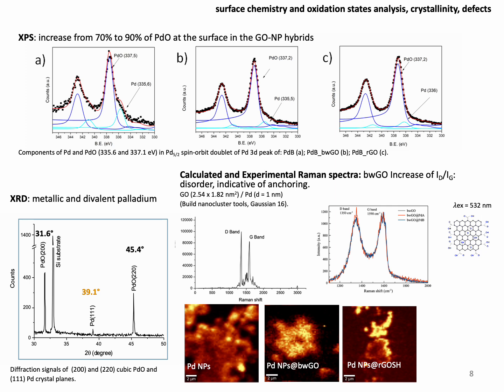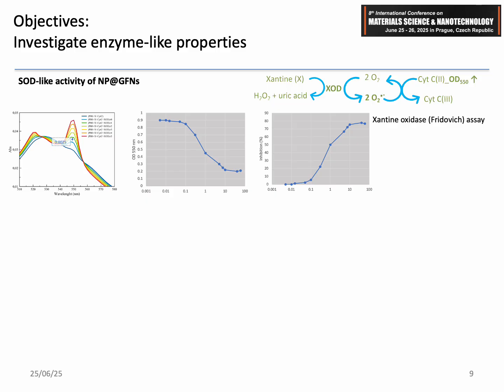This trend is also confirmed by the quantum mechanical Raman spectra calculation performed on the model systems using a Gaussian 16 model, built with a 2.54 times 1.82 square nanometers structure of graphene oxide and palladium nanoparticles with a diameter of 1 nanometer.